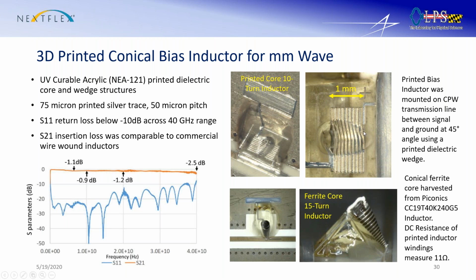So what we did, we took an SMT component, one of these, and we harvested the conical magnetic core out of it, and printed the windings. Again, Dan Hines printed the windings around the core. And we also printed this 45-degree wedge. The reason we do this is because the wide end of the conical inductor is the low frequency end. We want that separated from the ground plane as much as possible to minimize the coupling between that end and the ground plane, and the lower the frequency, the more coupling you get. So that's why we tip the